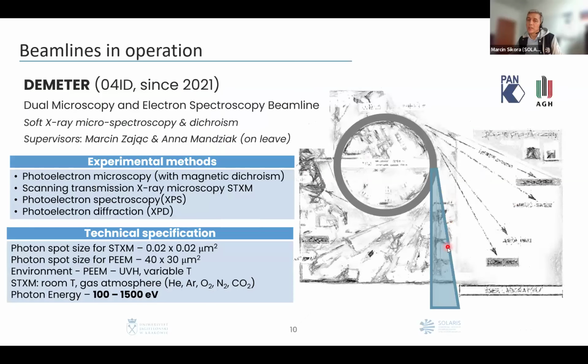So the other beamline that is closely related to PIRX is also soft X-ray spectroscopy, but in this case with microbeams. So we do microspectroscopy and also dichroism with 2 types of microscopes. So in this beamline, we have also the range of the energy from about 100 electron volts to about 1500 electron volts. But this beamline hosts 2 microscopes. So that's why it's a dual microscopy and electron spectroscopy beamline.